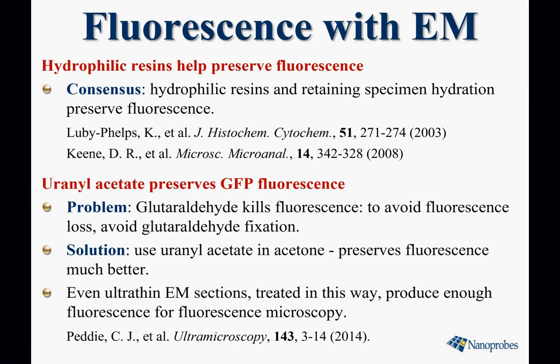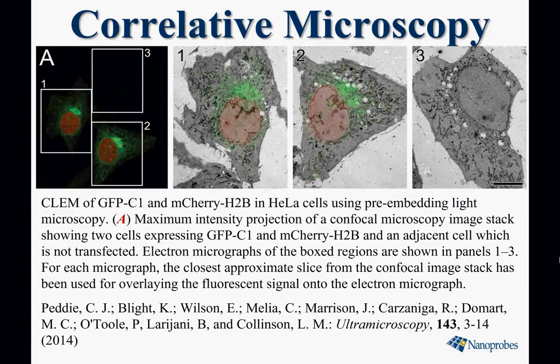Hydrophilic resins tend to preserve fluorescence. And here's a couple of references by Luby-Phelps and Keene for specific hydrophilic resins and specimen preparation methods that do help to retain the fluorescence at the EM level. Uranyl acetate preserves GFP fluorescence. Glutaraldehyde tends to kill fluorescence. So to avoid fluorescence loss, you have to avoid glutaraldehyde fixation. And Peddie et al. found that uranyl acetate is actually a good alternative and preserves the fluorescence much better. Even ultra-thin EM sections treated with uranyl acetate produce enough fluorescence for you to get both fluorescence and EM signals. And here's an example of that, showing the fluorescence labeling and the electron microscopic labeling.